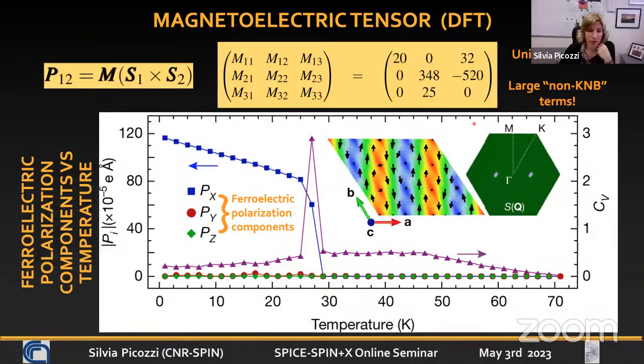And so by means, again, of Monte Carlo simulation, we did the spin helix, and then on top of each spin couple, we built our contribution to polarization, summed up over the whole lattice, and basically get a net polarization along X, which is perpendicular to the plane in which the spin rotates. The other components are 0, and it's peaked exactly at the same Curie temperature. So you basically have that ferroelectricity pops up below the magnetic ordering temperature.